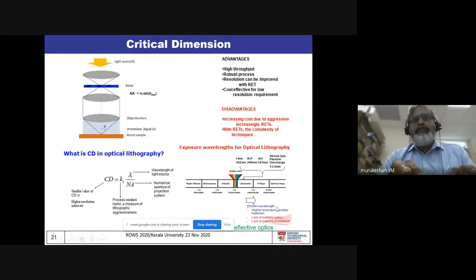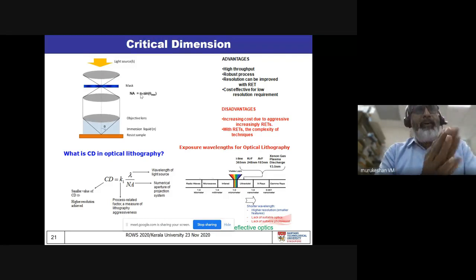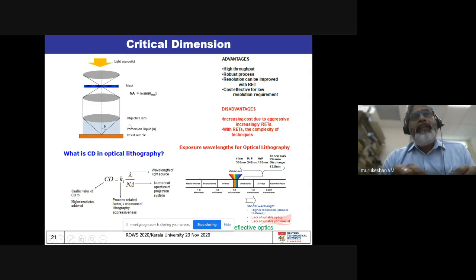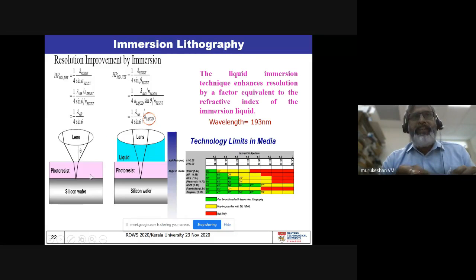So the lack of suitable optics and lack of suitable photosensitive material such as photoresist is going to play a very important role there. So the next question is, can you increase this numerical aperture? Then also you can reduce this. If you want to increase this number, either you have to increase the refractive index, or you have to play with this sine theta. But there is a limit to how much you can play with the sine theta. The only option is to increase the numerical aperture. So what people have normally done to increase this resolution is widely known as RET, resolution enhancement technique. They try to manipulate the refractive index of the medium in between. They used some high index fluid between this lens and the substrate, which is later known as immersion patterning or immersion lithography.